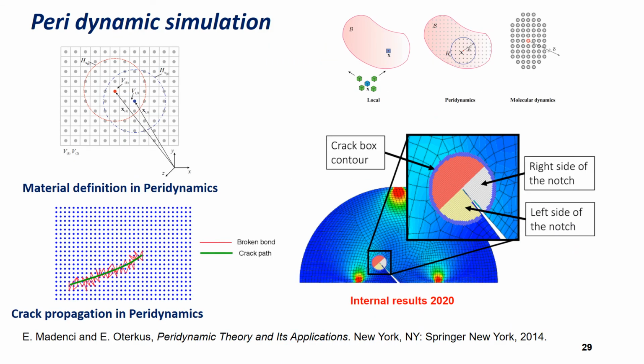The peridynamic simulation theory is an extension of the standard theory of solid mechanics compatible with discontinuities due to the presence of cracks. The principle is to treat the material as an assembly of discrete points linked together by specific bonds. During deformation, when the deformation exceeds a certain threshold, bonds will break and cause nucleation or extension of the cracks. Consequently, the initiation and the growth of cracks spontaneously emerge from a peridynamic simulation without the need to define beforehand an initiation and propagation criterion, which requires a lot of experimental parameters.